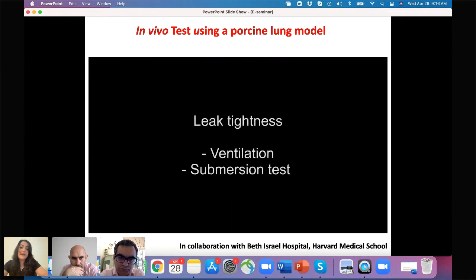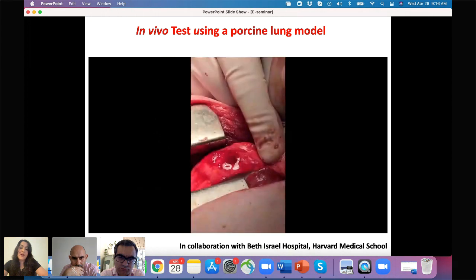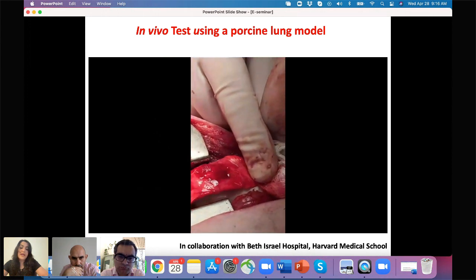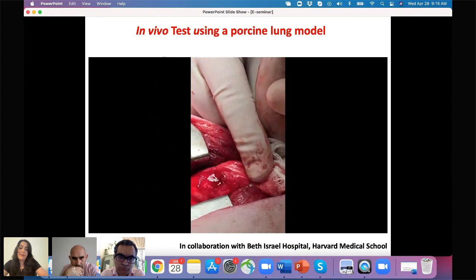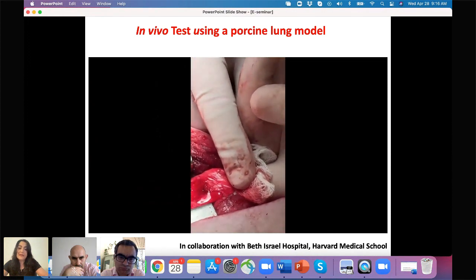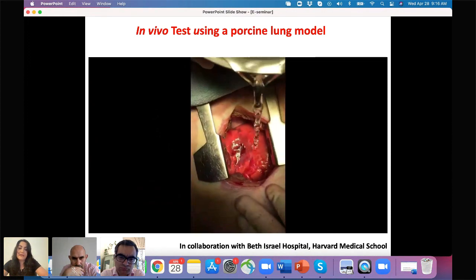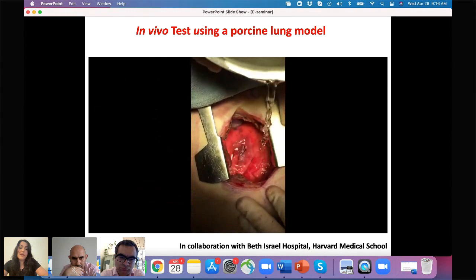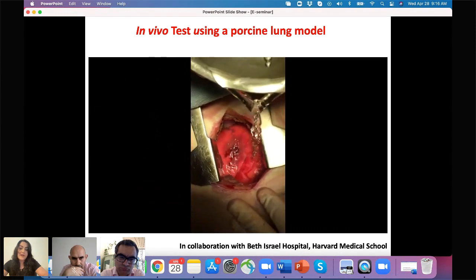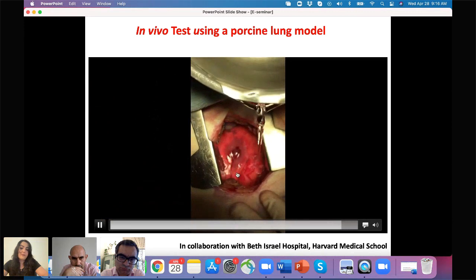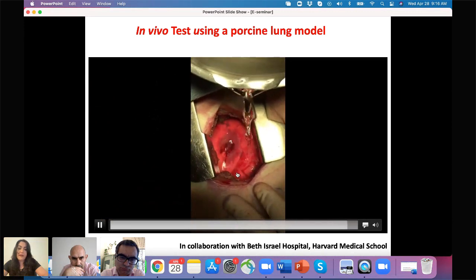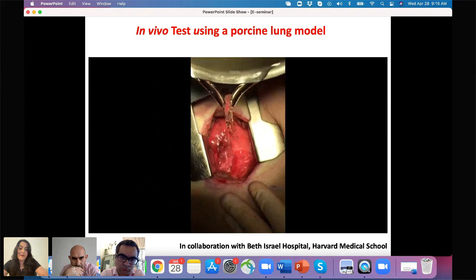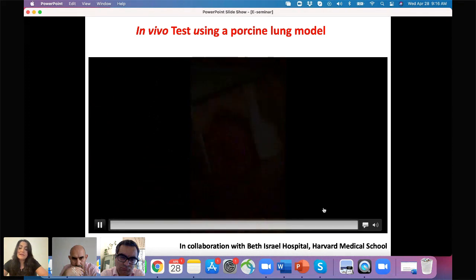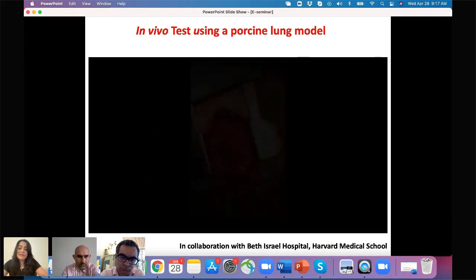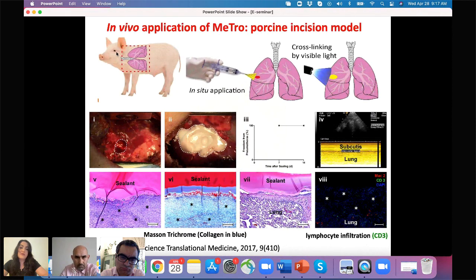And then we check the air leakages from the defect site, by connecting the line to a ventilator and applying liquid or PBS on the surface of the sealed defect to ensure that there is no leakage around the defect site. So here we observe complete stop of blood or air leakages from the sealed defect. Once we confirmed that there is no leakage, the chest was closed and we kept the animals for 2